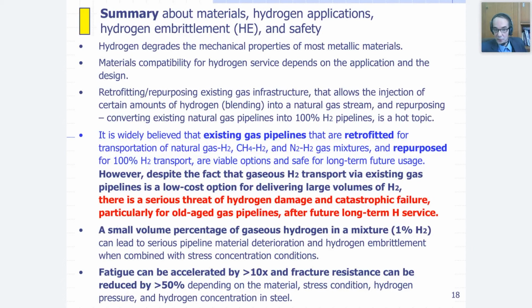But, however, despite the fact that gaseous hydrogen transport via existing gas pipelines is a low-cost option for delivering a large quantity of hydrogen, I want to point out that there is a serious threat of hydrogen embrittlement, hydrogen damage and catastrophic failure, particularly for old-age gas pipelines, and particularly after future long-term service and transportation of hydrogen in, for example, gas pipelines with pre-existing defects on the inner side. So we need to implement a structural integrity model for estimation of safety of such pipelines.